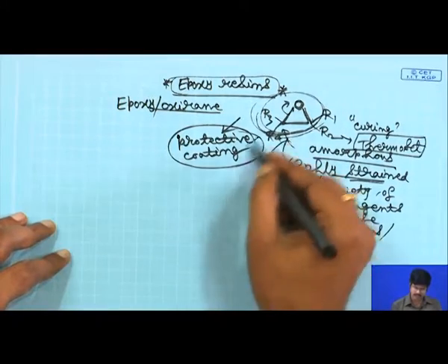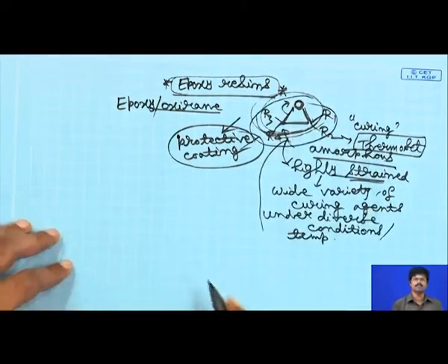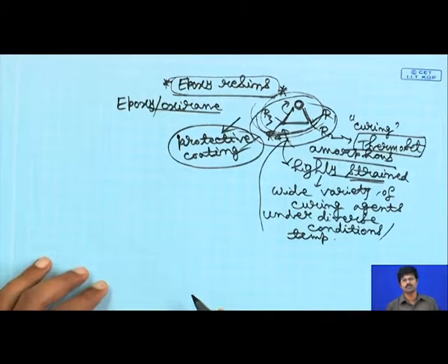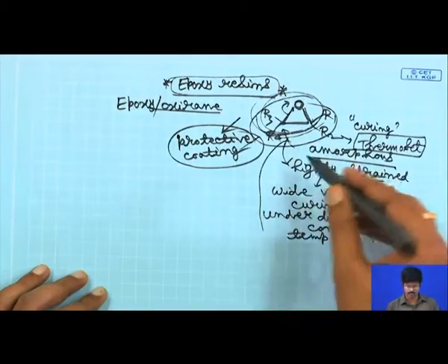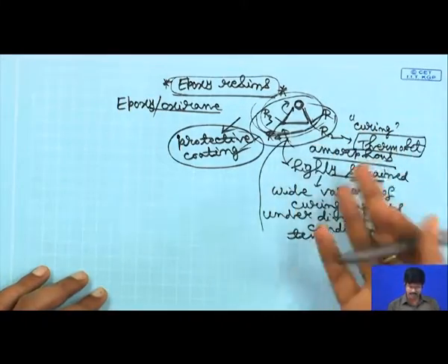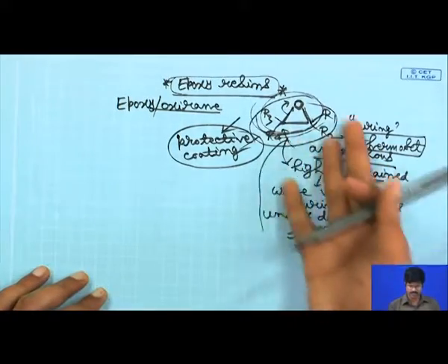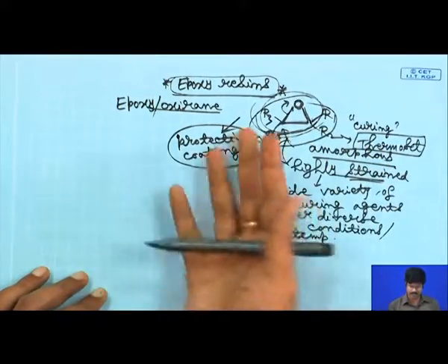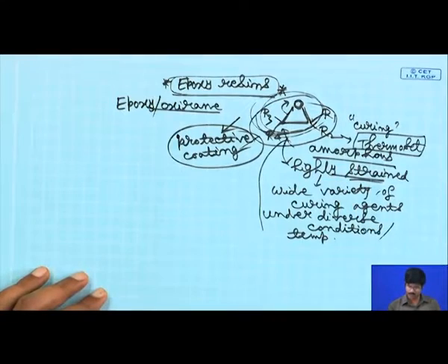So, that is what imparts versatility to these epoxide linkages, because ultimately you are going to get thermosets by opening up these epoxides and cross-linking different chains, and these are highly strained, as I have already told, and a wide variety of cross-linkers or curing agents you can use.